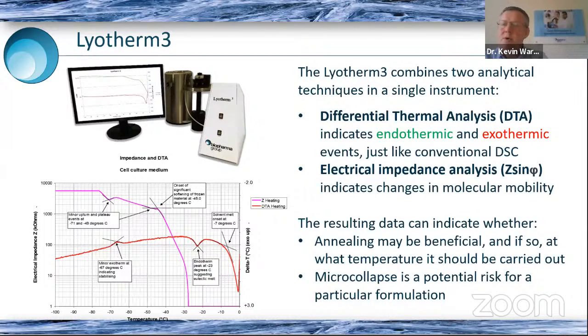Instead of using resistance, which only tends to be very good for very polar and very ionic molecules, so small drug molecules would be a classic example of something where resistance would work, he had found that by looking at impedance instead, that will give far more detailed information as to what would be happening in more complex formulations, which maybe contained more biological molecules. And so we worked with Professor Louis Ray. He very kindly collaborated with us to produce Lyotherm2 about 14 years ago, and we've since developed Lyotherm3, which has a slightly expanded impedance range.